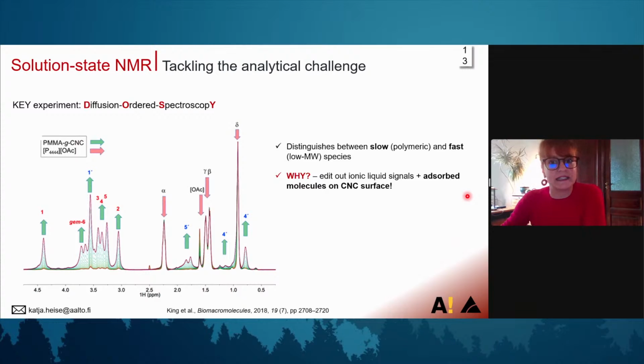And what we can basically do is that we distinguish the diffusion coefficients of slow diffusing polymer compounds from fast diffusing low molecular weight compounds. So why do we do this? It's also described in Alistair's article from 2018. We do this to edit out, first of all, our ionic liquid signals, also the DMSO, and also residual water, and also to get rid of all adsorbed compounds on the cellulose surface. So with this method, you can actually really say something is covalently attached.